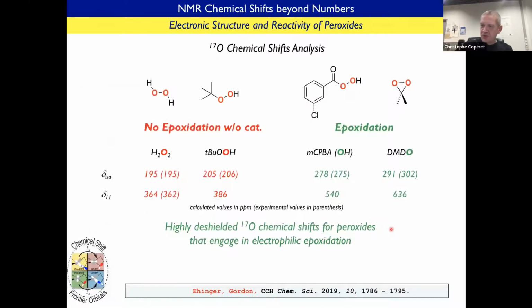It's something that comes back to my postdoc years, when I was with Professor Sharpless. What I noticed when I was working with Professor Sharpless is that if I look at metal peroxides, there are two types of peroxide. You have H2O2 and TBHP, which are peroxides that do not allow the oxidation of olefins, what we call epoxidation. And there are peroxides like MCPBA and DMDO, molecules with a cyclic structure, which allow epoxidation. If you look very closely, the ones that do not allow epoxidation have a chemical shift around 200 ppm, while the ones that do epoxidation have a chemical shift around 300 ppm.